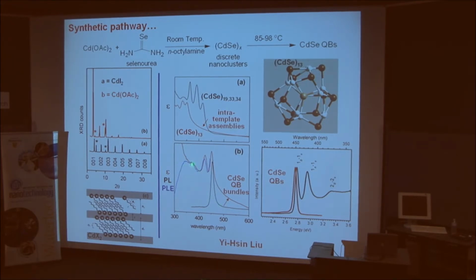And this is what you see. You see 3 features in the absorption spectrum and 1 in the emission spectrum. These 3 features are assignable to quantum well, or one-dimensional quantum confined, structures. Again, there's a long scattering tail because these cadmium selenide belts are still trapped within the template structure. Now, when we unbundle them, we get this spectrum, and you can see the scattering tail is gone because we've taken the bundles apart. And here you see the assignments of the quantum well absorption features.